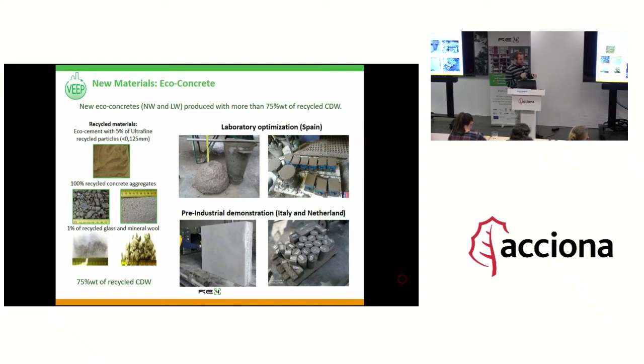At the beginning, we optimized the concrete at laboratory scale here in Spain, Tecnalia and Acciona. And afterwards the challenge was to upscale the production to a pre-industrial scale. When we optimize a formulation at laboratory, it's not easy, but the conditions are controlled, and we can control the production. But when we upscale the production of the concrete, it's always very complicated because of the mixing process, and the operating conditions are very different, and normally the properties of the concrete are quite different. So the challenge here was to upscale the production to an industrial scale. And the pre-industrial demonstration was performed in Italy and the Netherlands in a precast company.